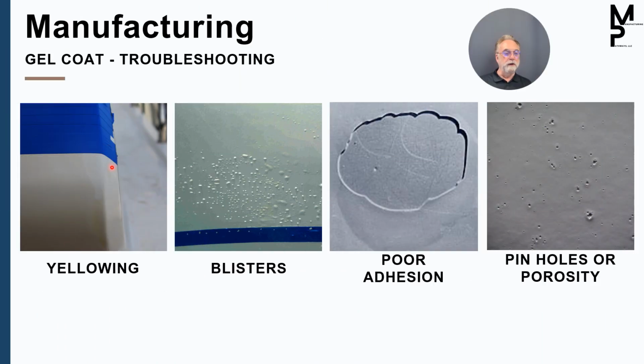Okay, yellowing can be caused in a repair process. If we thin the resin out with styrene, instead of using patch aid, we can get this kind of discoloring effect, particularly in a repair.